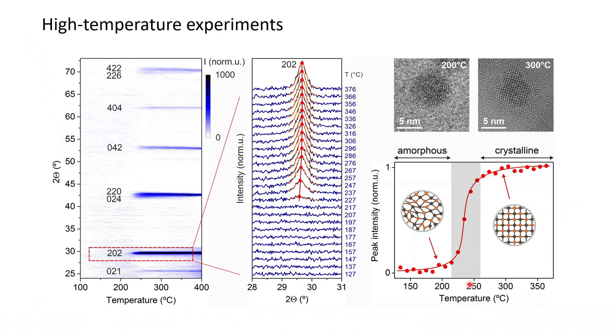Shall we basically heat this material to see what's going to happen? And then we did that. We measured X-ray diffraction at different temperatures, and at some point we start to see the peaks appearing. These peaks tell us that we have an ordered material. So our disordered material at low temperature becomes ordered at high temperature. You basically see a close-up of one single peak here, and from nothing arises something.